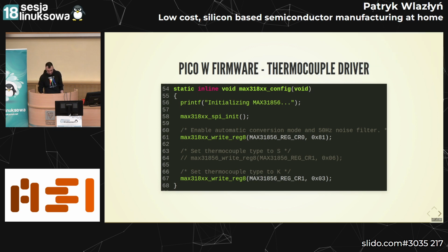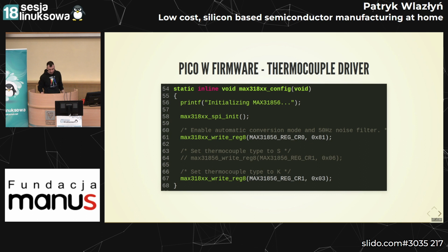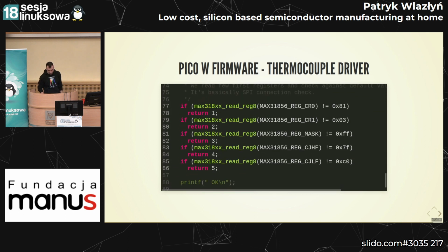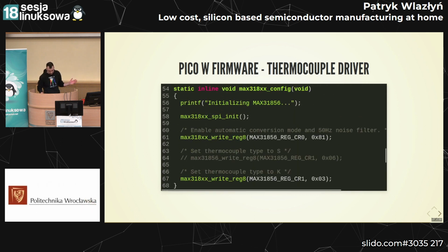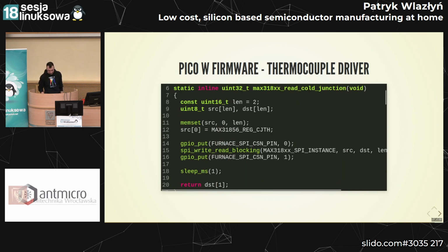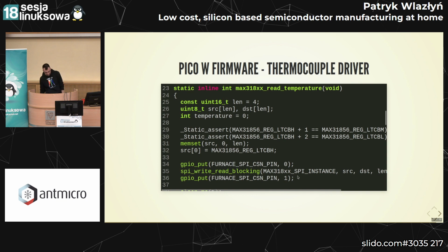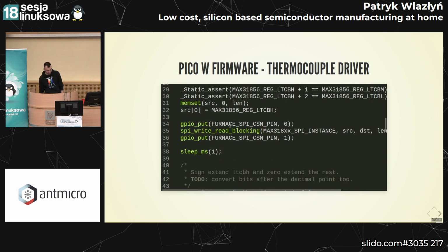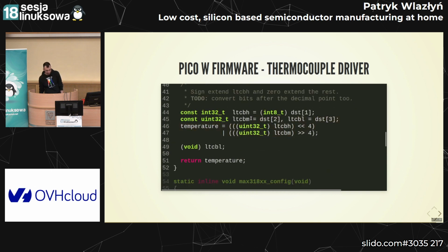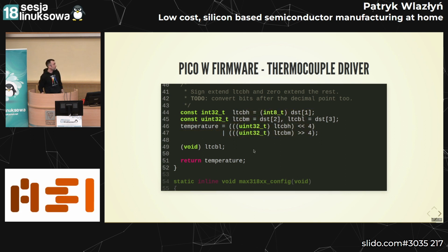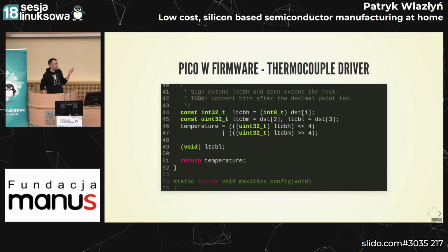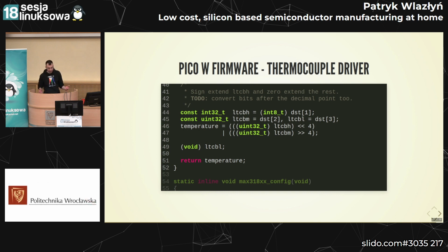And there is a simple SPI interface for the driver for the thermocouple we are using. The main point here is that for the initialization, you just do 2 writes on the SPI, and later reading the temperature comes down to 1 SPI transmission and shifting the values from two registers to form a temperature. So it's a very simple setup. You just take a driver and a thermocouple, and you can measure high temperatures between like 0 and 1500 degrees C.